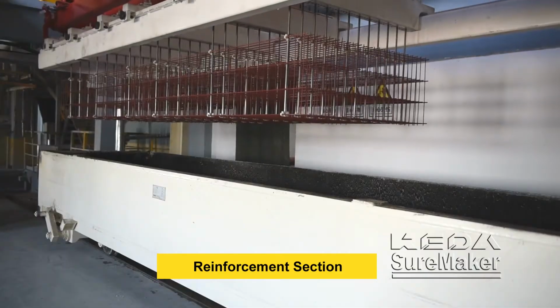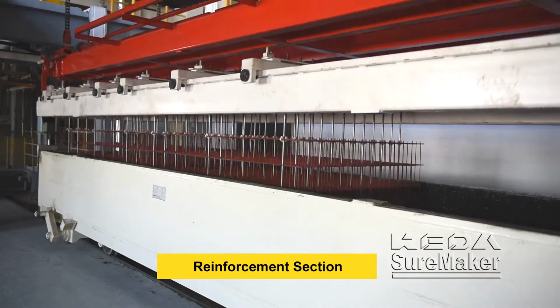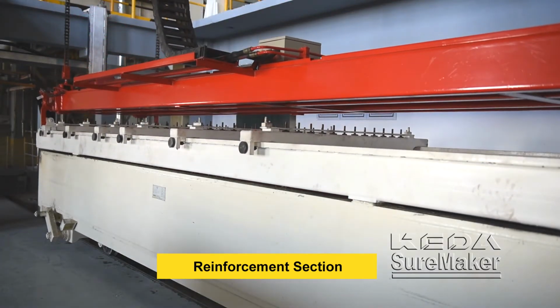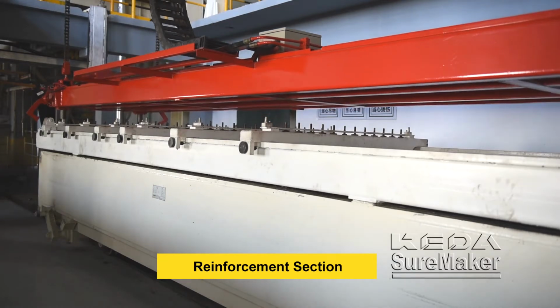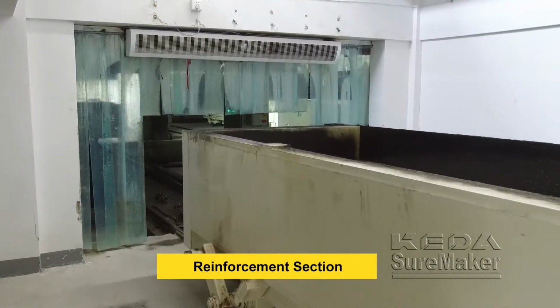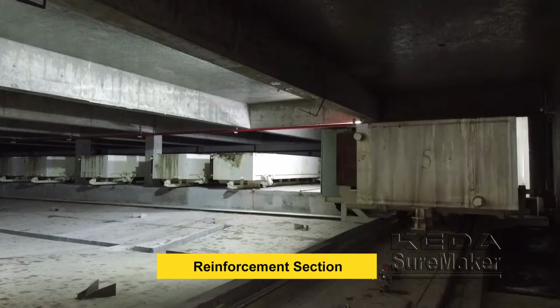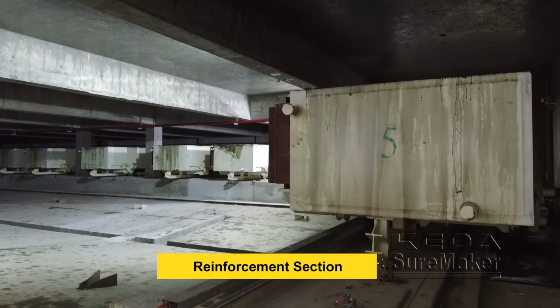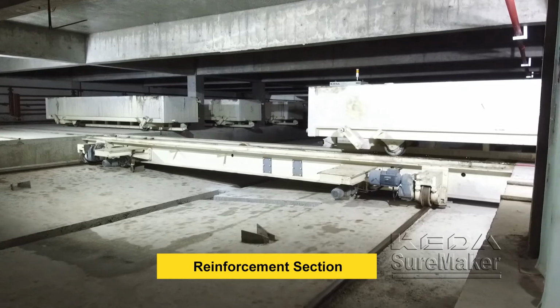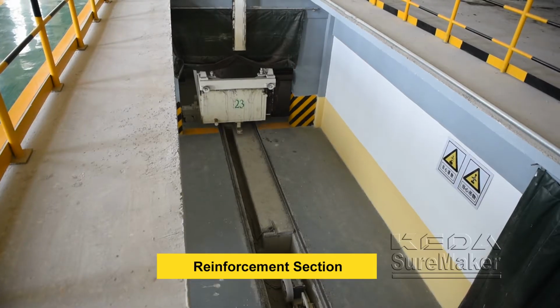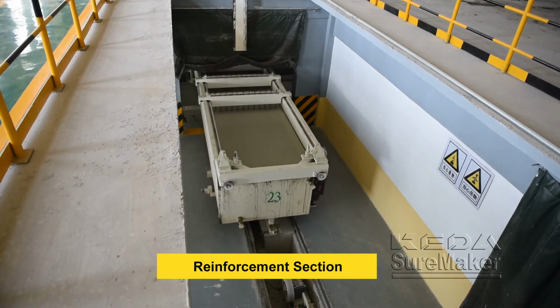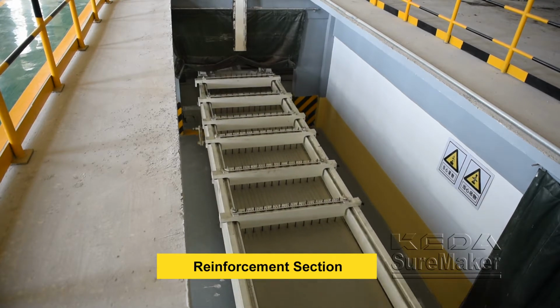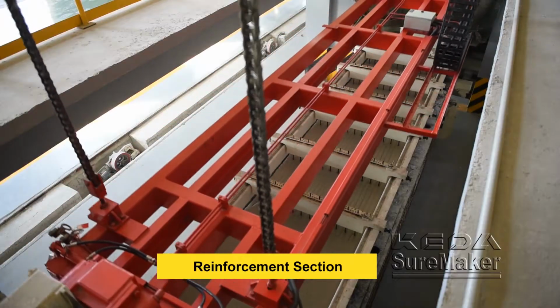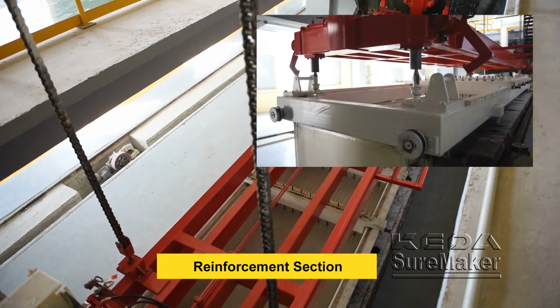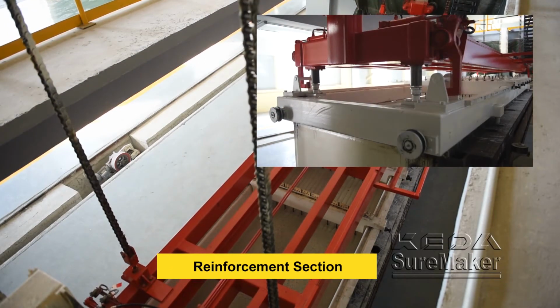After pouring, the steel mesh cages are inserted into the slurry by the saddle frame and then transported by ferry car to the pre-curing room. The temperature of the pre-curing room is around 40 to 45 degrees Celsius. The needles will be taken away from the green cake after pre-curing. Then the cake will be transferred to the cutting section through an insulation passage.